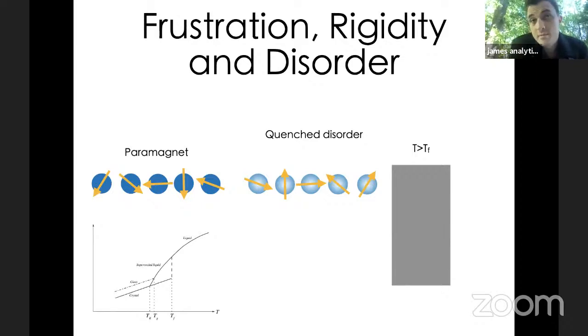Now, in a magnetic system, there is an analog of this kind of supercooling, which isn't completely identical, but it's similar. And that's what we call a spin glass. Now, in the case of a spin glass, it's not necessarily that you have to supercool a system. It's just that there's no actual time scale slow enough for the system to actually equilibrate, because there are so many long time scales in the system.